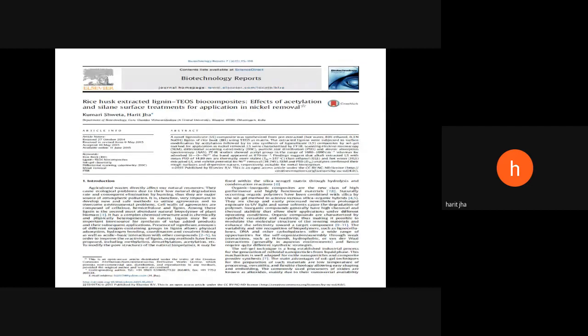This is another work which was published in Biotechnology Reports, a good journal, in which we have used rice husk extracted lignin with TEOS for synthesis of the biocomposite. Our idea was the use of an organic and inorganic hybrid, that is a silica and organic hybrid, using the sol-gel technique, so that we can achieve a polymeric composite which should have prolonged exposure to various conditions like UV, and should have higher strength properties and the other value added properties which we are looking for. So in this, we have used the lignin silica composite.